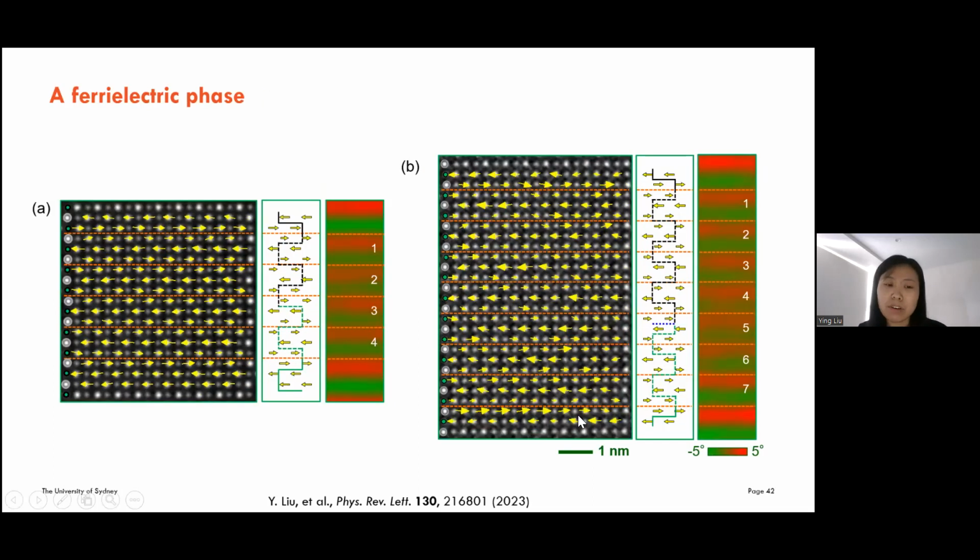But if it goes to 4 such units, it is not zero, because 4 such units can be perfectly replaced by 3 perfect antiferroelectric unit cells. So such a lattice must have a slightly lower energy than the antiferroelectric phase.